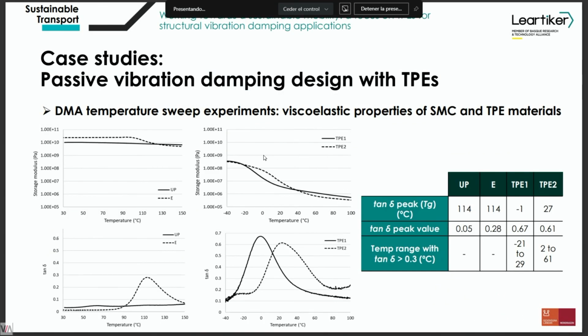Here you can see some dynamic mechanical analysis tests we performed. These are temperature sweep experiments, which give a lot of information about the viscoelastic properties of the materials, for example, in terms of material selection for product requirements when the product is under cyclic conditions. As I mentioned earlier, and as you can see in the graphs, the SMC materials, UP being the unsaturated polyester and E the epoxy, have a very high stiffness value, but the loss factor at room temperature, 30 degrees, is very low. So high stiffness, but bad vibration damping capability.